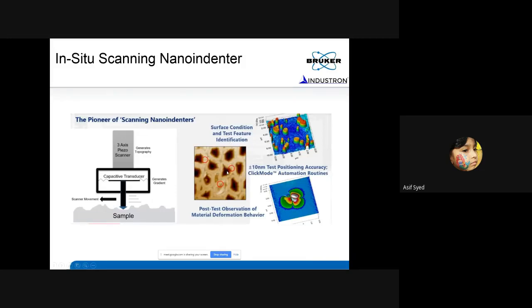So this is kind of a typical example I'm going to show you, where you can use this technology not only to see the surface by scanning probe microscopy, but then you can also pinpoint where you want to do the test and measure the force displacement response. Okay, so it is kind of a scanning probe microscopy you have in situ with your nanomechanical Nanoindenter test instrument. So you have both capabilities within one single instrument.